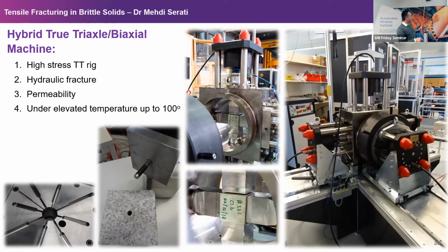And here, the grooves that you see at contact plates are where we are putting heating elements. So unlike some studies where you heat up the sample in an oven, you take it out, you load it up to understand how temperature impacts the results. Here in this machine, we have the luxury of the heating element sitting right at the back of the contact plate. So as you're loading it up, you can manage the temperature. So it's a direct coupled thermomechanical test.